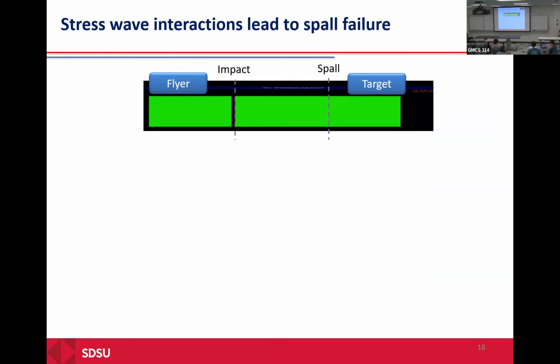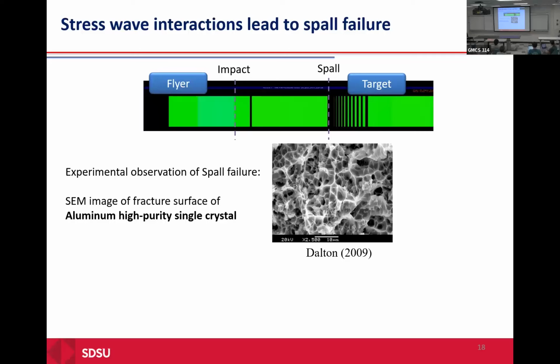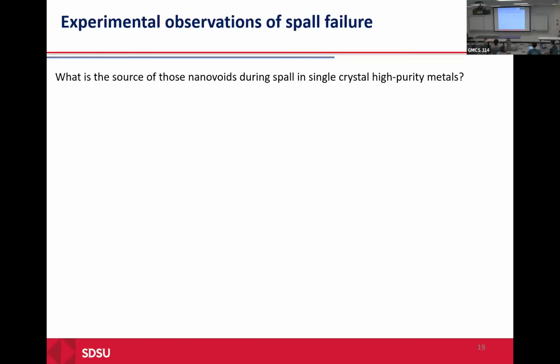This is another figure that shows, for example, the impact of the flyer on the target. At the place where the impact is happening, the waves are propagating, and when they come back as a tensile wave, they hit another place where the spall is happening. If we look at the microstructure of the material and the experimental data that we have, at the place where the spall is happening, this is a sample of high purity single crystal aluminum. We see some dimples on the material. Then we want to see what the source of these dimples is at the place where the spall is happening.